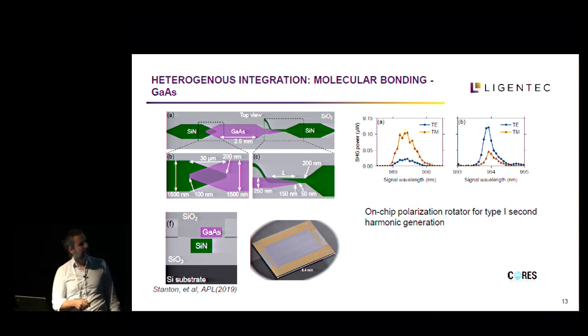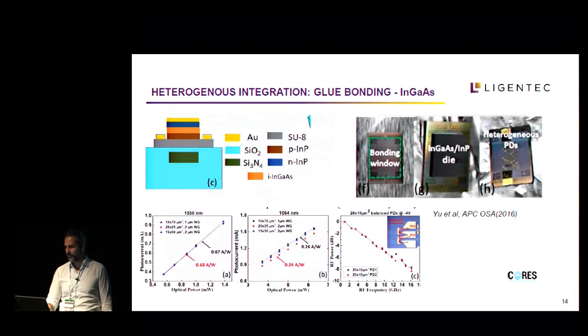And you can see here that you go from a dominant TM mode to a dominant TE mode. And again, the wavelength that this thing operates at is unique. So you can do that around 1 micron, the second harmonic generation from, if I remember well, a 50-50 pump.